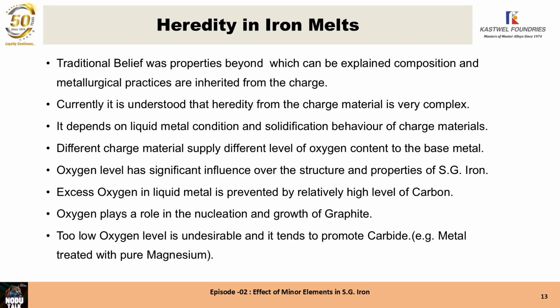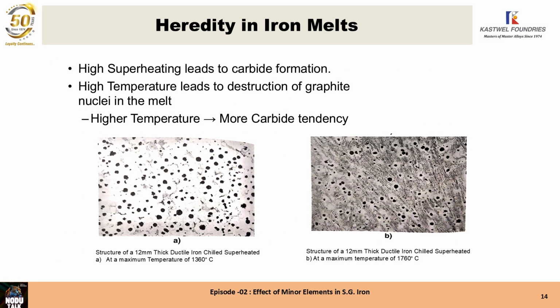Next slide, please. Superheating the metal leads to carbide formation. High temperature leads to destruction of graphite nuclei in the melt. There are two aspects to this. Higher temperature, more carbides. You see in the figure below, figure A is metal at the maximum temperature of 1360 degrees centigrade: no carbides, beautiful nodules, high nodularity, lovely nodule count. This is one of the most important requirements of SG iron.